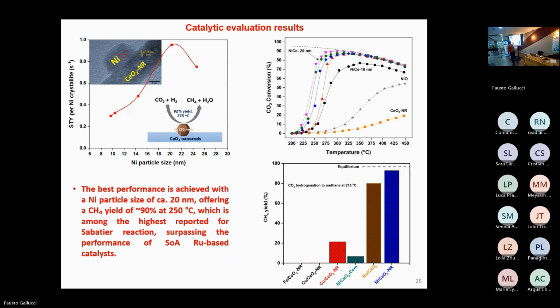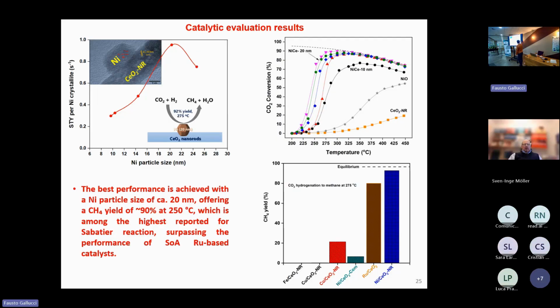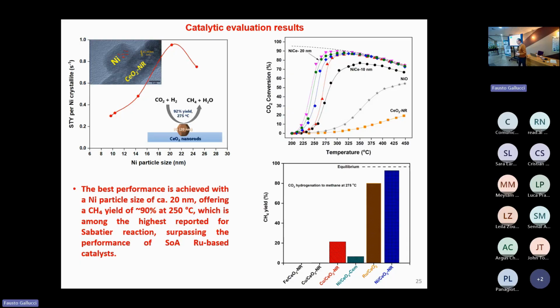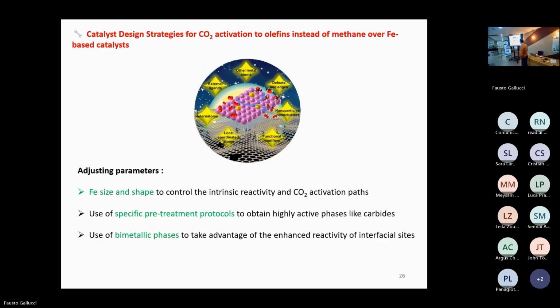And here you can see at a glance the catalytic evaluation results in terms of site time yield as a function of nickel particle size, carbon dioxide conversion, and methane yield. The best performance can be obtained by a nickel particle size of about 20 nanometers, offering a yield to methane of 90% at about 250 degrees Celsius, surpassing the state-of-the-art ruthenium-based catalyst, thus demonstrating the effectiveness of the proposed fine-tuning approach.